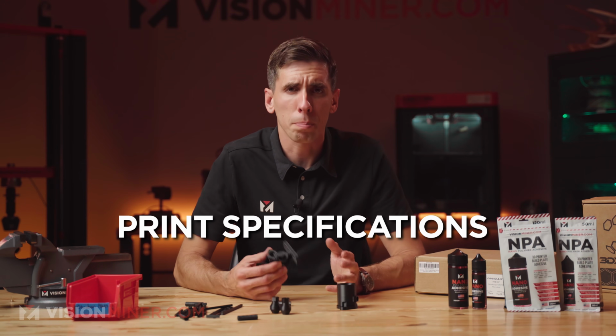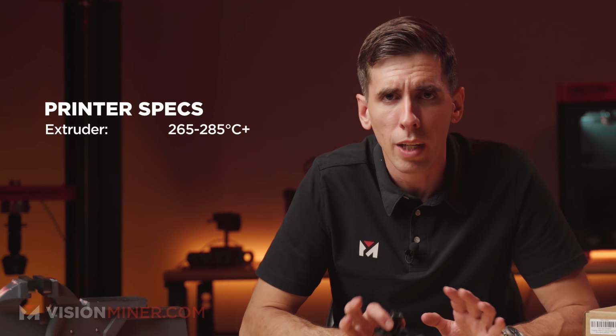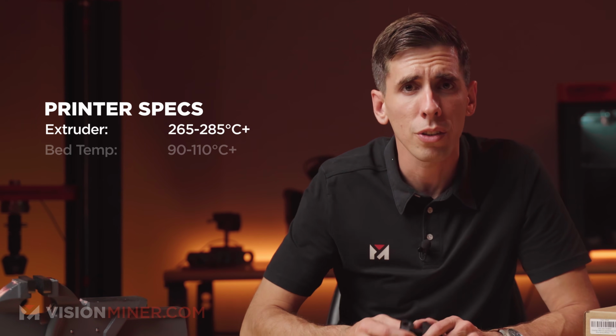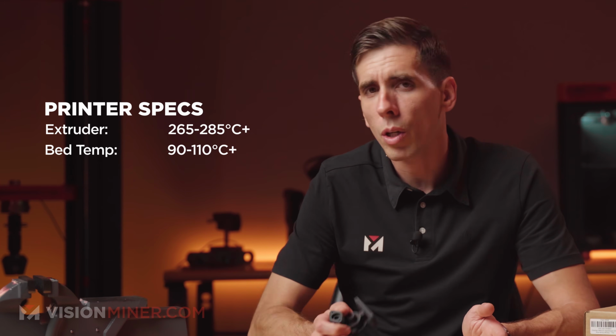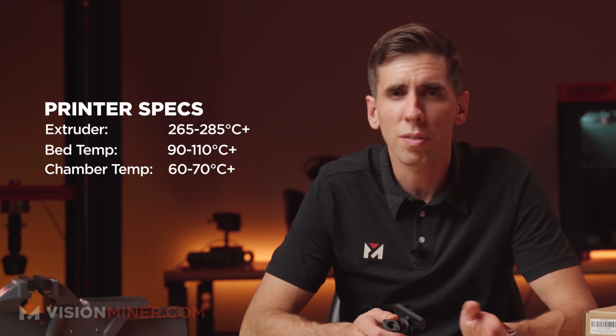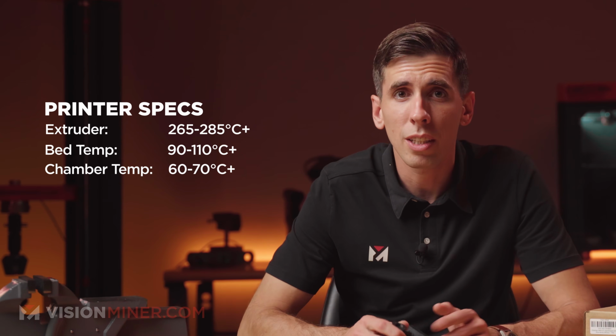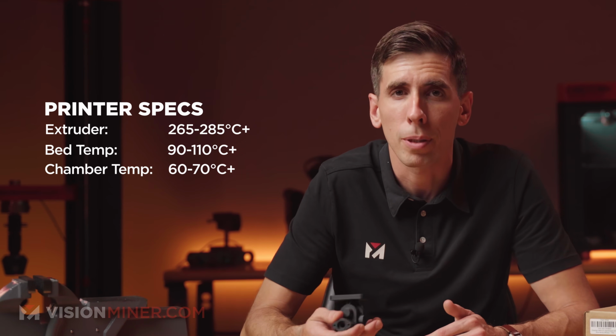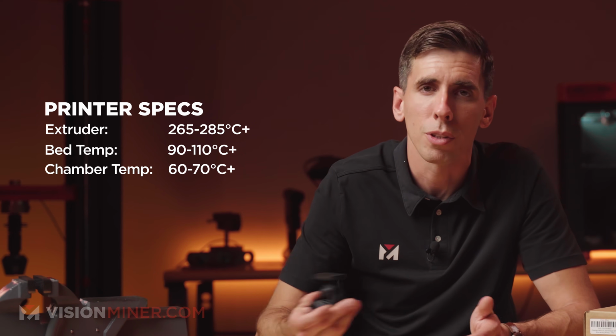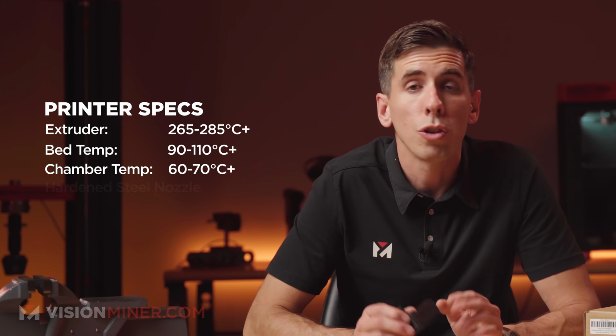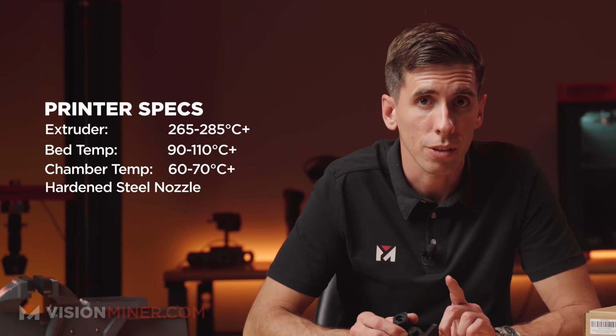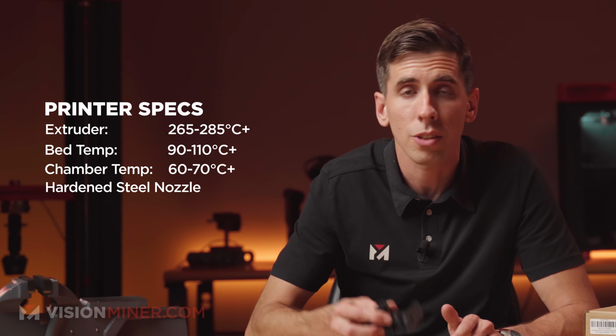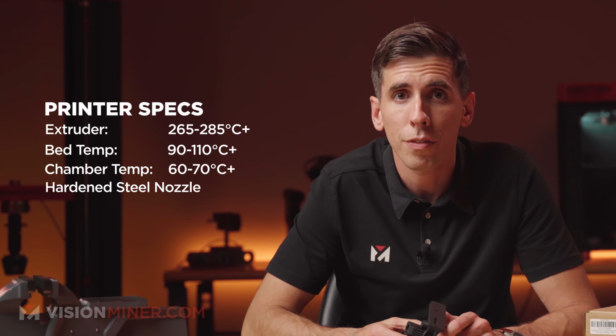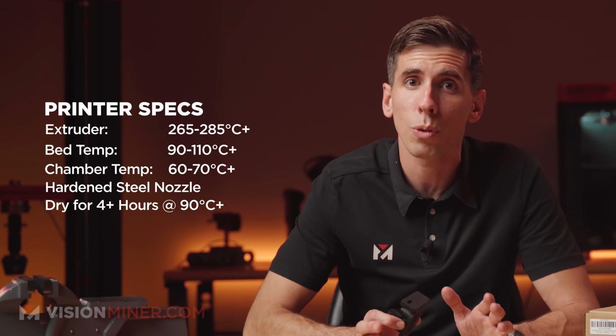So what do you need to print Obsidian? The setup we recommend, the minimum specs, is about 265 to 285 Celsius on the nozzle, bed temperature about 90 to 110 Celsius, chamber temperature about 60 to 70 Celsius, and that's optional, but it does help a lot. With any nylons, it's going to reduce warping and everything. Definitely use a hardened steel nozzle. This filament is going to chew through your brass because of the carbon fiber, and definitely dry it for at least 4 hours at 90°C.